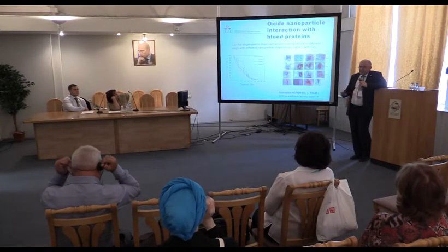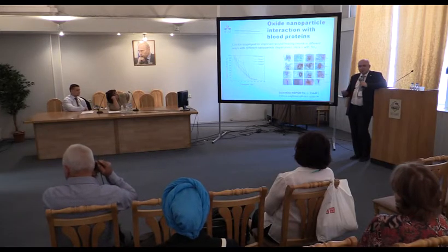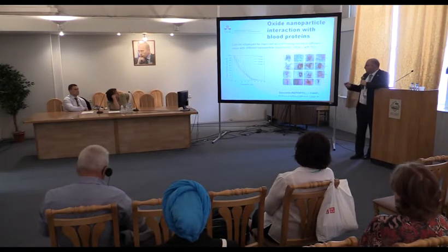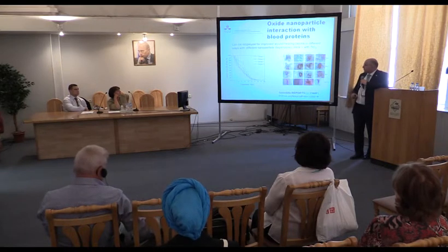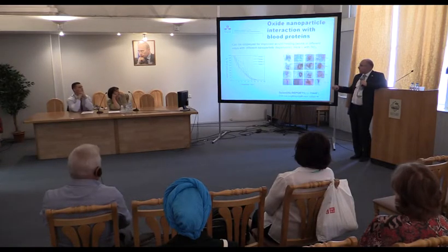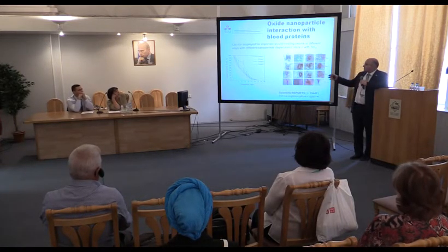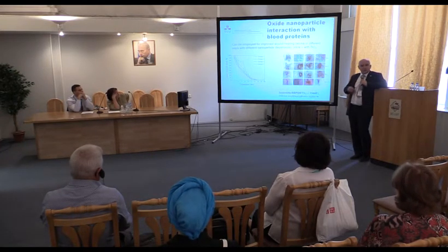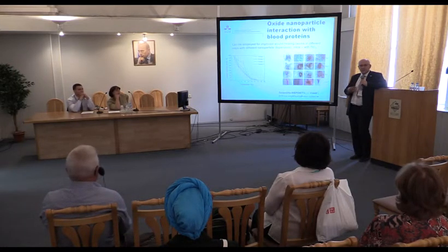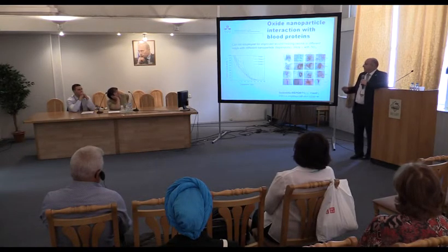Because we were inspired by this idea that titanium oxide should clot the blood, should stop the blood flow, we have, together with our colleagues at ITMO, and the results are published in this paper, in Scientific Reports, Nature Publishing Group, looked at what is happening when we add the dispersion into the blood. And what we could see, it's not in this image actually, was very increased and enhanced clotting, very quick formation of a hybrid material based on protein and titanium, which is solidifying the blood.